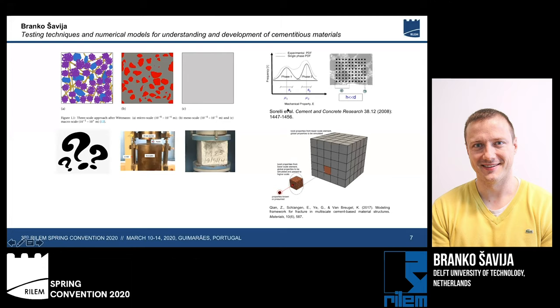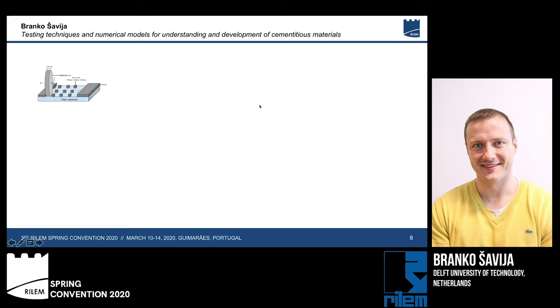But we are, of course, not only interested in elastic properties, we're also interested in fracture and in strength of our materials. So we try to develop techniques that will enable us to mimic this process in predicting mechanical properties of cementitious materials. So we developed a technique to prepare very small cement paste samples by gluing a very thin layer of cement paste on a glass substrate and dicing it using a precision saw, as shown in this figure. And we end up with a matrix of very small cubes of hydrated cement paste, which we will then use to test and measure its response to mechanical loading.